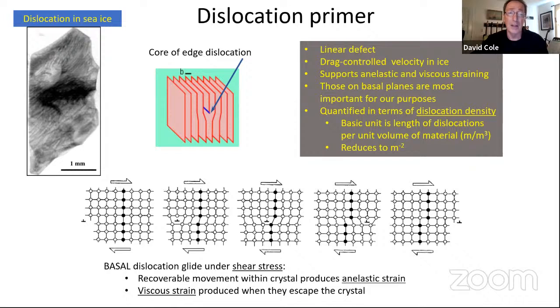But all the black lines are dislocations. So there's plenty of evidence of a lot of dislocations in sea ice. And so that gives rise to a very strong anelastic component. So physically, there's no issue with the concept of a lot of dislocation activity in sea ice, even unstrained.